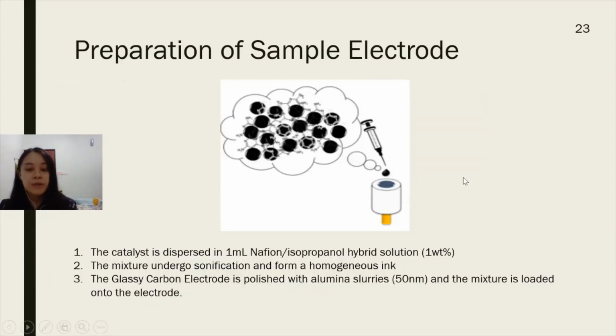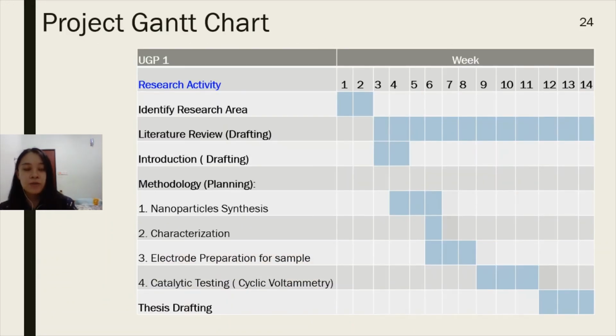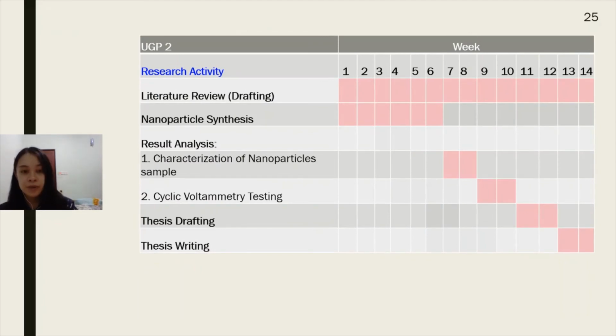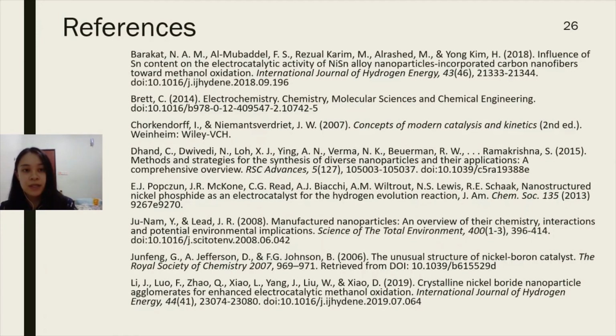While for the sample electrode, we will have to prepare by dispersing the catalyst or nickel boride nanoparticles onto Nafion/isopropanol hybrid solution and undergo sonication to form a homogeneous ink. And then the glassy carbon electrode will be polished by alumina slurries, and then the mixture will be loaded onto the glassy carbon electrode. So this will be my project Gantt chart for UGP1 and also UGP2, and these are the references that I have used.